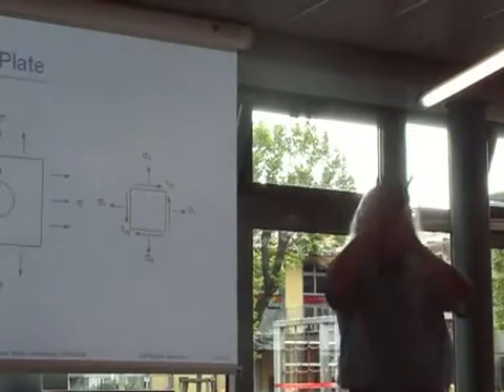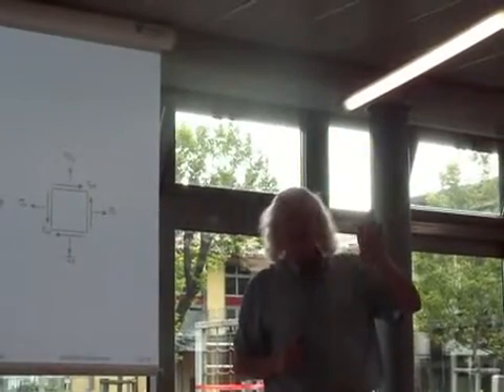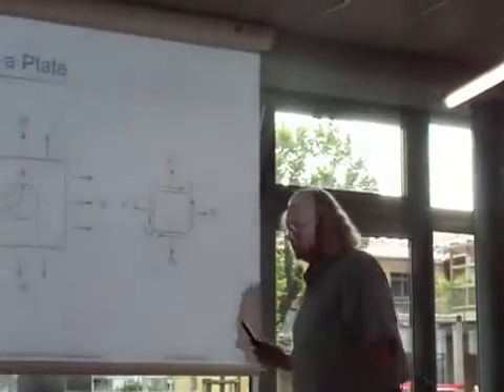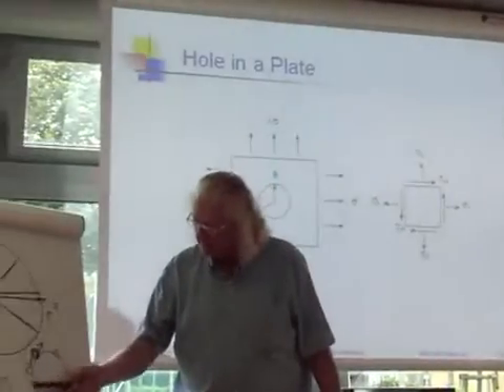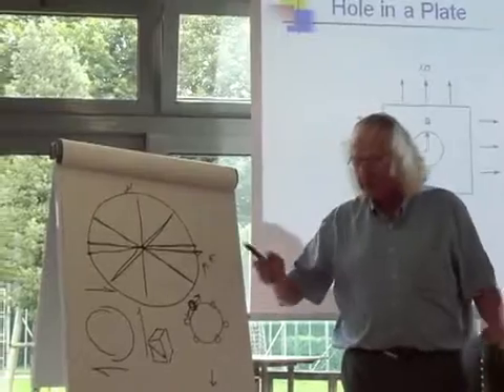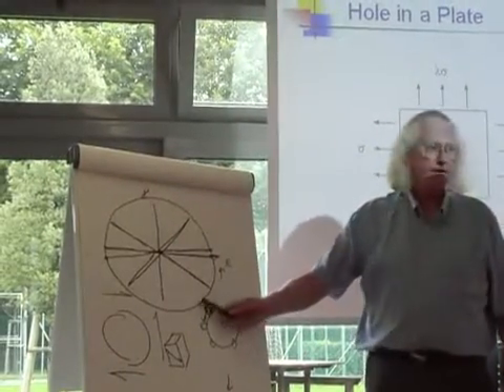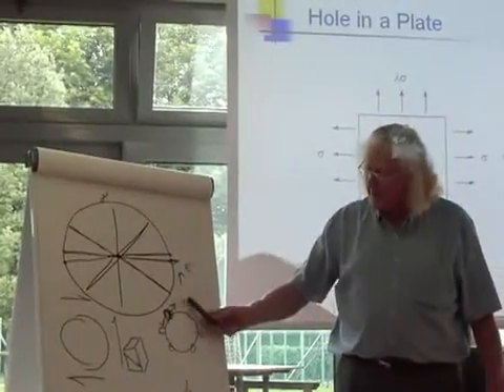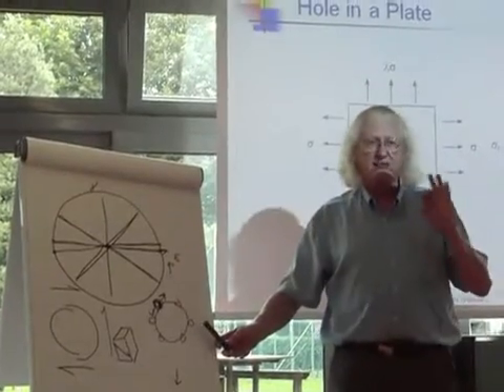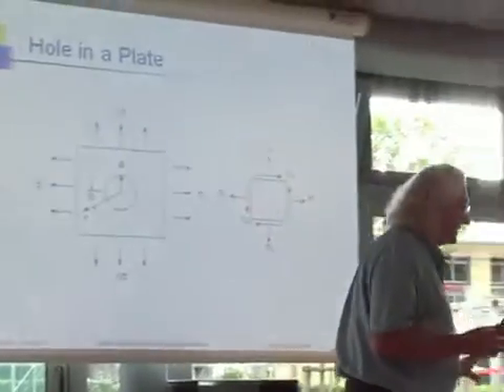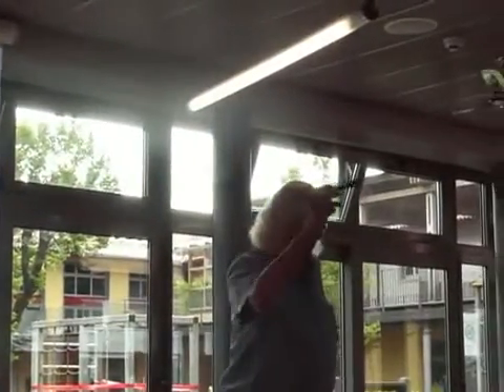And that's why I say that if you have plate-like structures, plates with holes in them, or things that look like plates with holes in them, it's really not a multi-axial fatigue problem. Maybe the failure location changes, because if you look at the different stresses around the edge of the hole, depending on whether it's loaded in shear, tension or biaxial tension, then of course the magnitude of the stresses around the edges of the hole change, and the location of the maximum stress around the hole changes, but the state of stress is simply uniaxial tension. So that means that the real multi-axial fatigue problems come from solid structures. Things like shafts and turbine blades and things that have a lump of mass of some sort. Because there you truly can build up multi-axial stress situations.